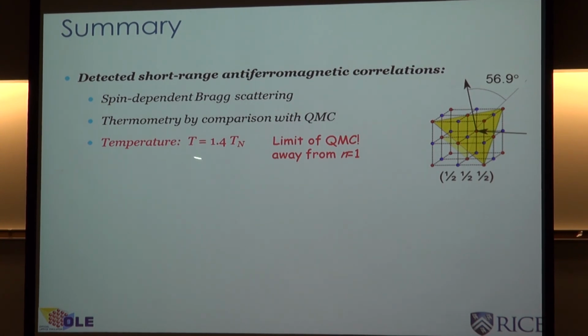Now, the interesting thing about this magnetic order is that we're at the limit of the QMC. So it took them literally months to be able to calculate these curves. And that's because when you go away from half filling, there is something called a sign problem in the calculation, and it requires a humongous amount of computer time to get decent statistics. So we're literally at their limit.